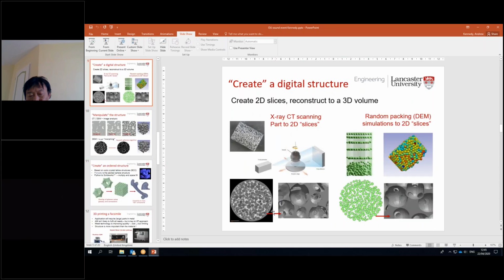So the voxel size on these are typically at around 15 to 20 microns. Okay, thank you. So reasonably decent resolution. I mean, it's all obviously about balancing resolution versus field of view. Of course, we could go to higher resolutions, but we are still looking at the importance of the RVE size for modeling these random structures. Unfortunately, we need quite big RVEs for them to be size independent. So yeah, it's juggling that balance really between the level of detail.